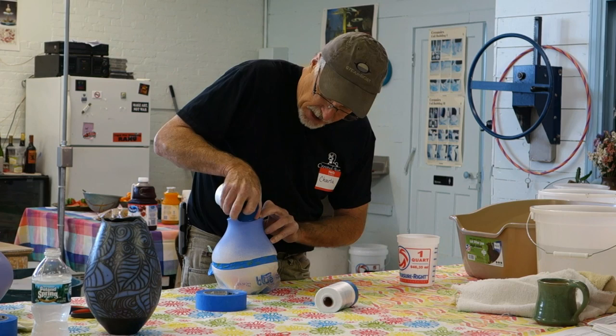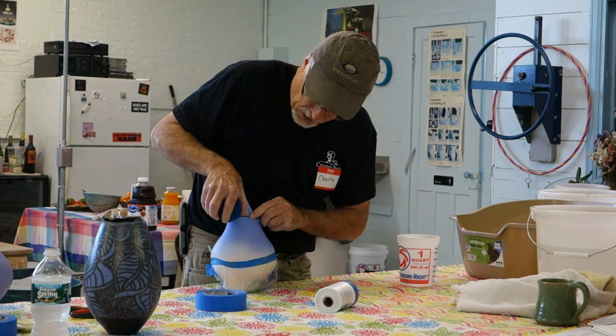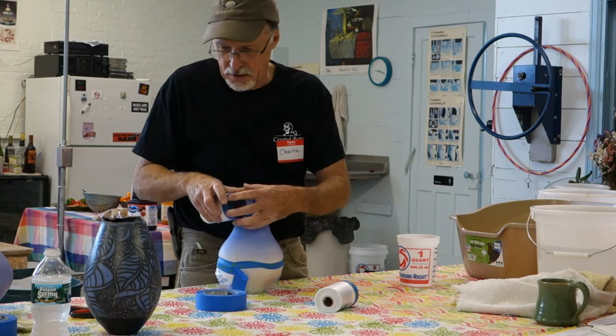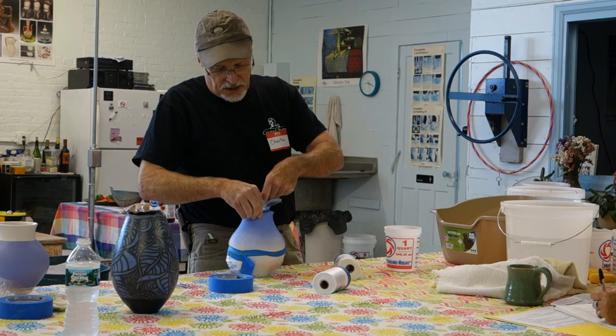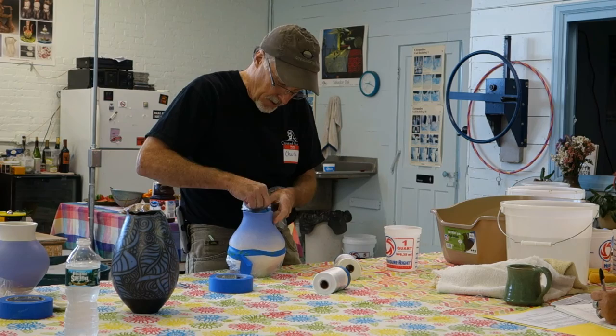The stained sigillata isn't as shiny, and one of the things I will be doing is getting a rock tumbler and some porcelain tumbling beads used in ball mills, and ball-milling the sigillata so it's a little bit finer. I cut this and, instead of trimming it down, I want to make sure the inside of the pot is protected from drips, so I'll just push it down into the pot so it'll catch drips.